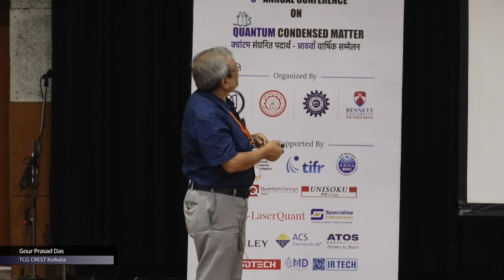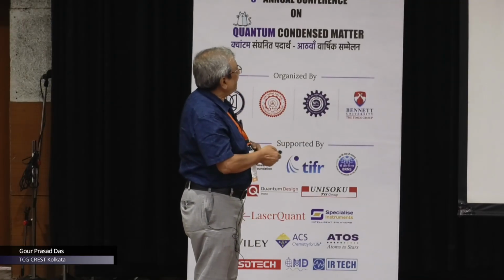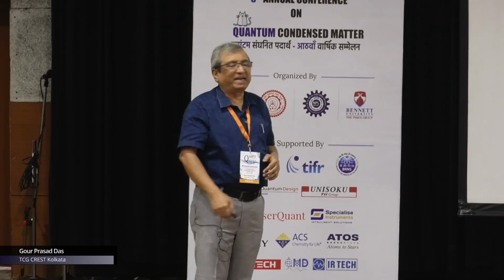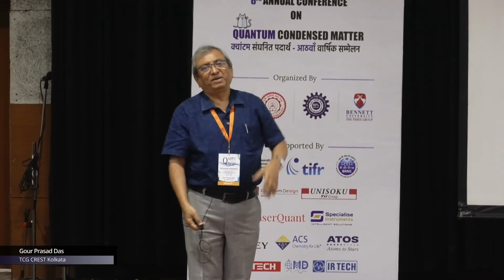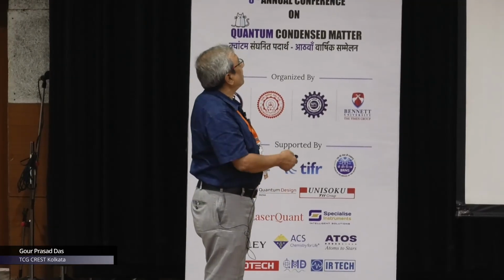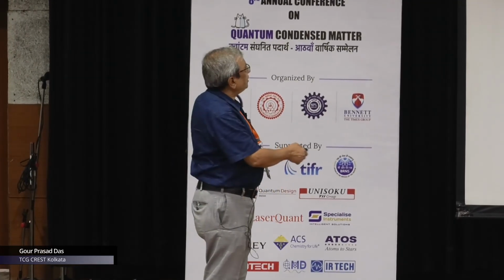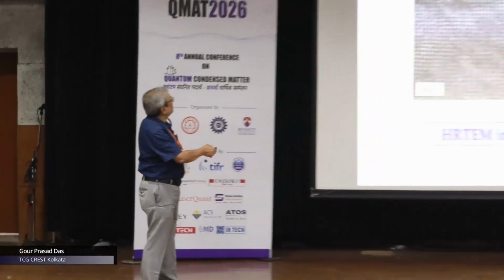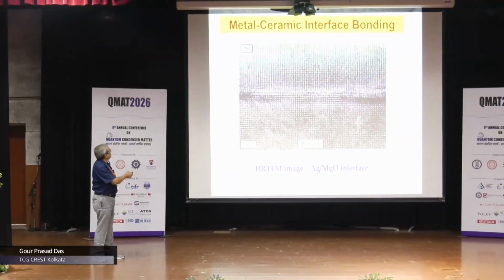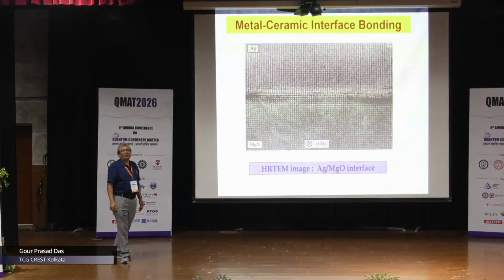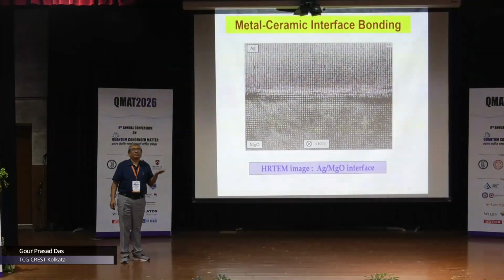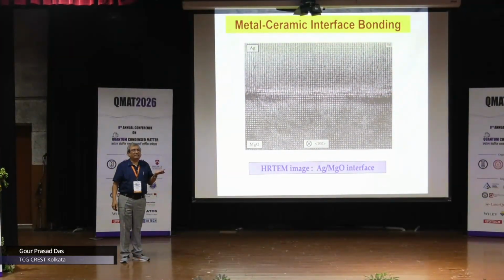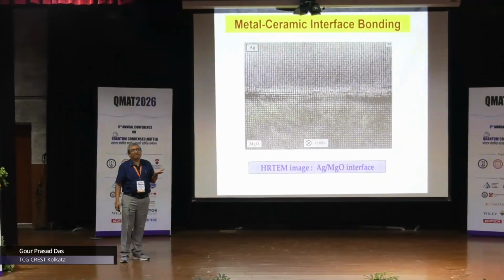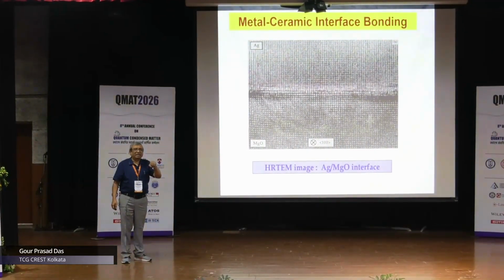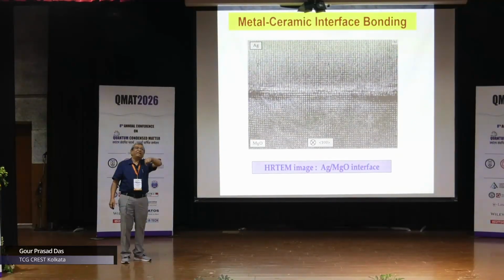Okay, so the metal ceramic junction is very, very important. So now this is an example of a metal ceramic interface bonding between silver and magnesium oxide. As you know, magnesium oxide is a large band gap insulator. It's a ceramic. Silver is a metal. Why am I showing you this? This is also a reasonably good interface between silver and magnesium oxide. I'll tell you the story. Some of the experimentalists approached us and said that, look, when we are trying to put that silver, after some time the metal was peeling off. That means the bonding was not good.